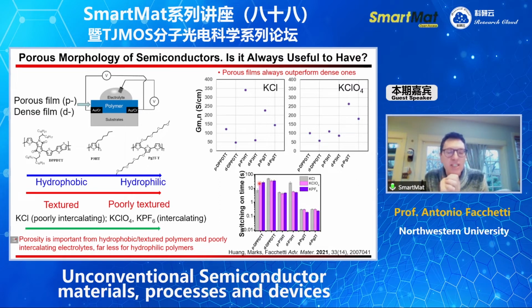So to summarize, because there is a lot of data and I don't have a lot of time: is porosity important? Typically you can enhance the transconductance in all cases. However, having porosity is very, very important if your semiconducting polymer is hydrophobic and very textured, and if you have an electrolyte which is poorly intercalating. However, if you have a very hydrophilic semiconducting polymer, it doesn't really matter if you have porosity. No matter what, the ions can intercalate. So with porosity you get a little gain, but not as much as you would have with a much more hydrophobic polymer. So porosity can be important or not, depending really on the combination of your semiconductor and the electrolyte.